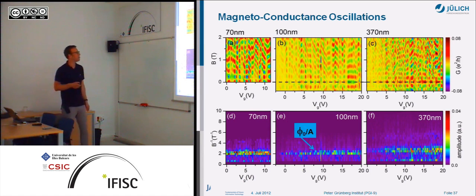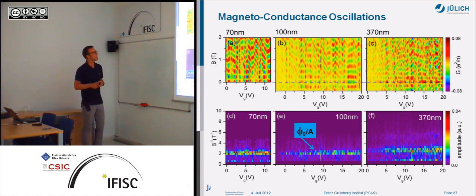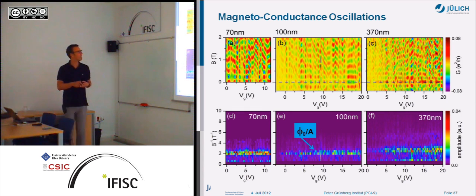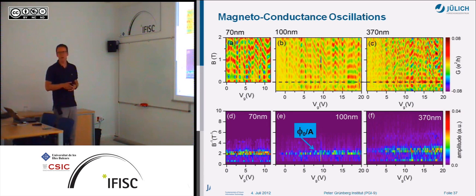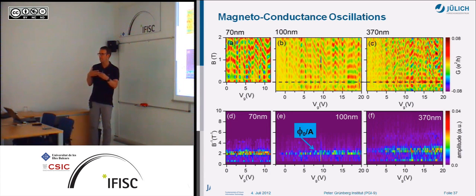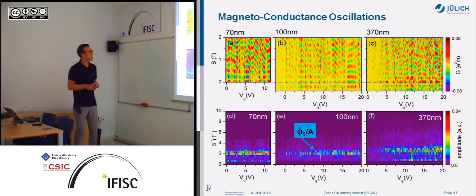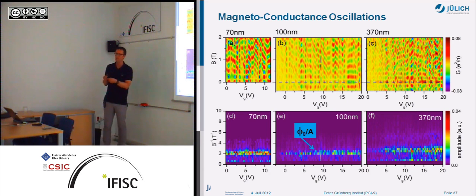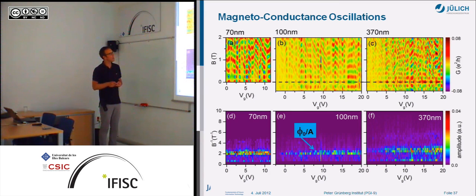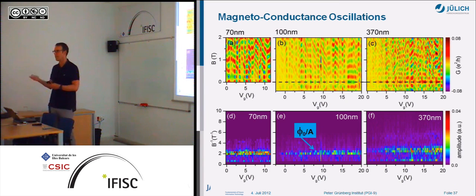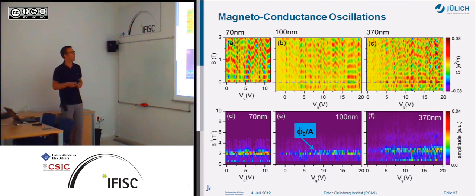This is more colorful, but basically the same. What you see here is the conductance color-coded. This is the gate voltage, this is the magnetic field. This pattern tells you that we have all the time the same period, but we have some phase changes. This is because depending on the gate voltage, you change the interference conditions, and because we have a two-terminal measurement, we have either a maximum at zero magnetic field or a minimum. Because we have a two-terminal conductance, because of the Onsager relation, this has to be symmetric with magnetic field. This is all true for 70 nanometer, 100 nanometer, and 370 nanometer lengths of the nanowire segment.